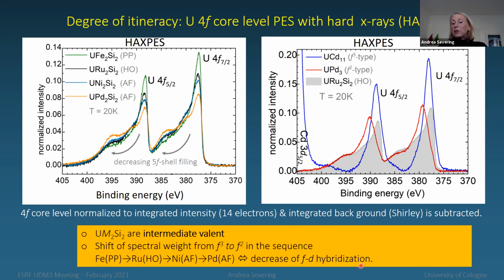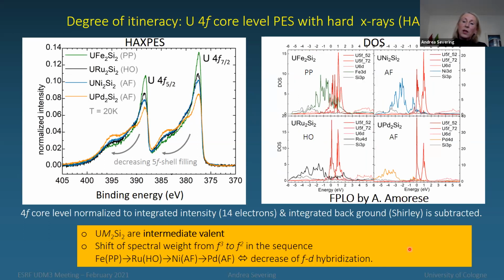Hence, we figure we are seeing in that sequence, as we see the decrease of 5f shell filling, a decrease of f-d hybridization, and that very much agrees with the calculation of the density of states by Andrea Amorese that I'm showing you here, again for the iron, the ruthenium, the nickel, the palladium, in red the uranium 5f states, and in the same color coding the respective d states. And what we're seeing here is the more F3 we have, the closer are the d states, the more they are overlapping, and the broader also the 5f states. So we go from the uranium iron to the ruthenium, here we're going down. We go to the nickel, we're going down, and we're going even further away, we go to the palladium, which has the lowest F3 and the most F2.